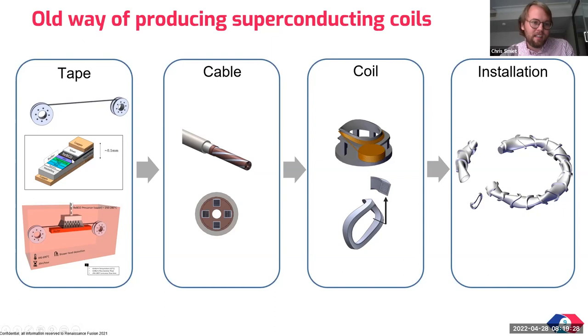The entire stack is about 1/10 of a millimeter, but it's just 4 micrometers thick of this superconductor in the entire tape that carries all of the current. And it's a rare earth REBCO type superconductor. Now we have these tapes and they need to somehow be put into the stellarator. So there's an intermediate step of making a cable. And here we show the VIPER cable concept, where the tapes themselves are put inside of a groove.